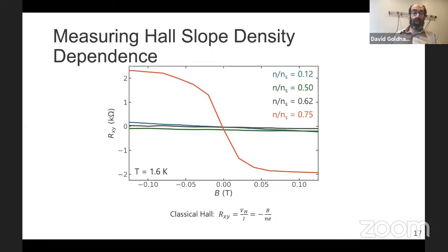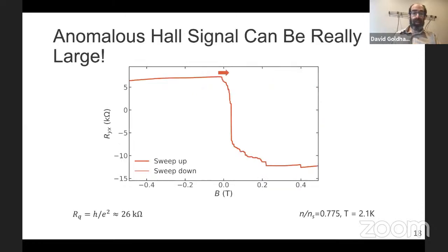So now I'll show you a measurement in our dilution refrigerator of the same thing. You can see that sweeping magnetic field over a slightly broader range, you get a sharp step as you go through zero magnetic field. And quite strikingly, when we go back in the other direction, there's hysteresis. The fact that there's hysteresis in magnetic field tells you that this is a magnetically ordered state. That's really quite striking. If you look more closely, you can also see there are multiple jumps here that suggest that if this is a magnet, it has multiple domains.